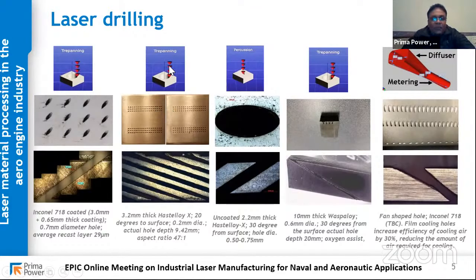This is another example of trepanning holes, very small holes, very closely spaced. Again, it's a challenge. This is Hastelloy X, 20 degrees to the surface. Typical diameter is 0.2 millimeter. If you look at the aspect ratio, which is 47:1, the actual hole depth is around 10 millimeters. This is percussion in an uncoated Hastelloy X, which is 30 degrees to the surface.